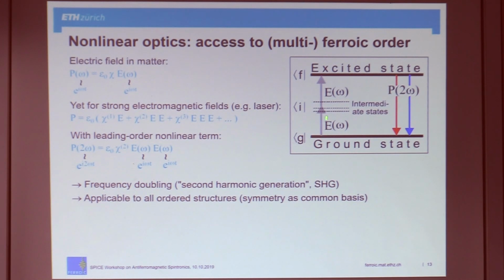So we take the simultaneous absorption of two photons from a light field, and then the relaxation in a single step. Energy conservation requires, you can also see it from writing down the frequency arguments, that the incident light is at omega, the emitted light is at 2 omega. This process is called frequency doubling or second harmonic generation, SHG. It's extremely sensitive to symmetry. This is why it's perfect for studying ferroic order, because any type of ferroic order breaks, by definition, some point group symmetry. Point group symmetry breaking is picked up by this process. You just have to look at the group theory, and then you will find an electrically polarized light wave that is only there because you have broken symmetry by some ferroic order.